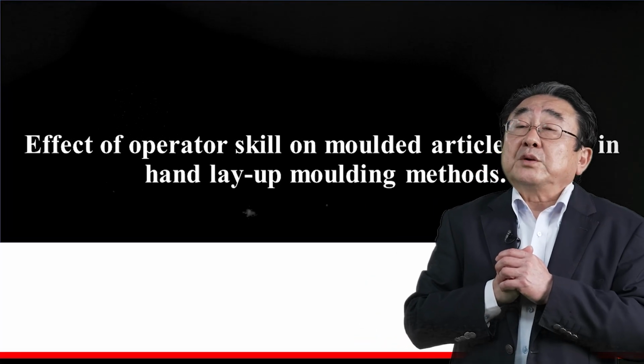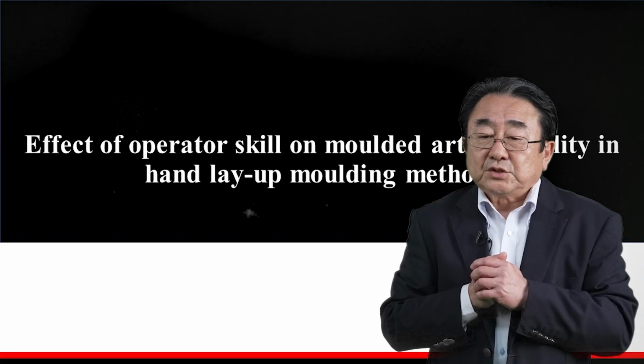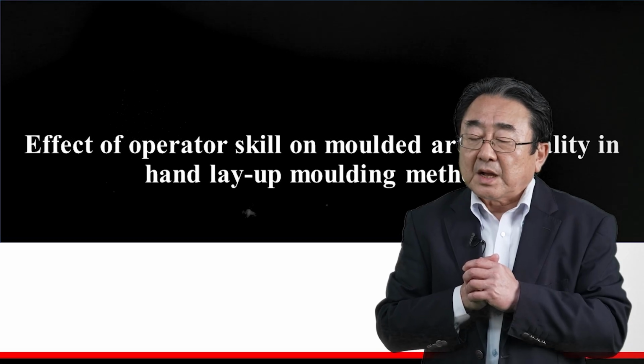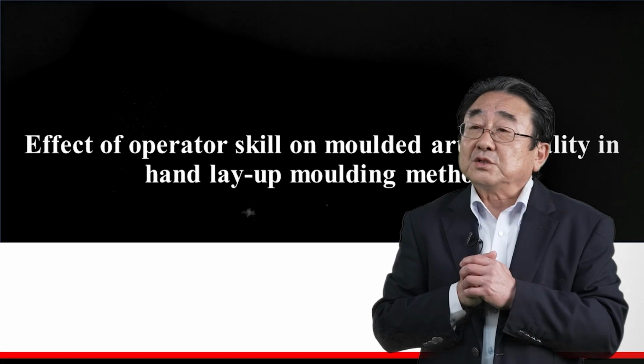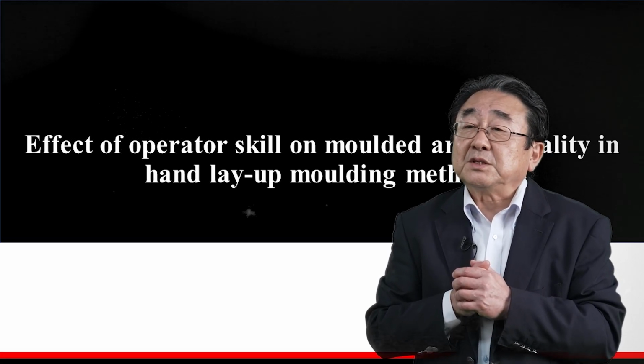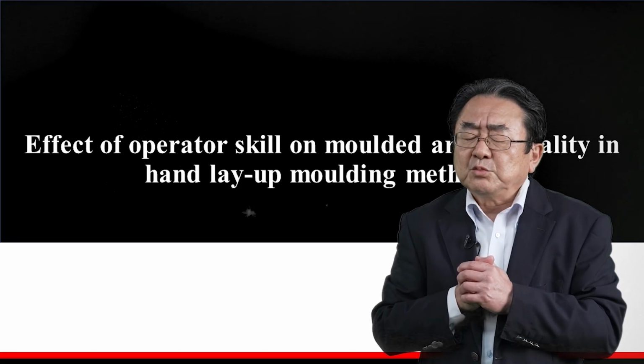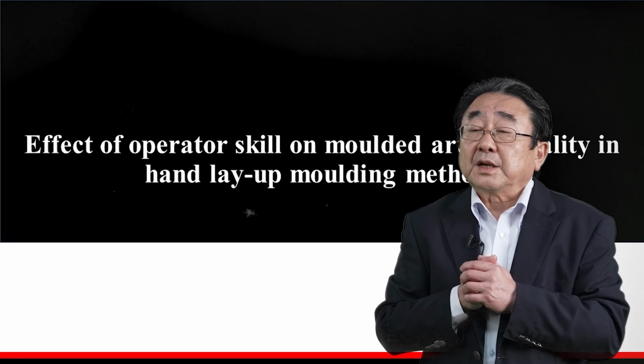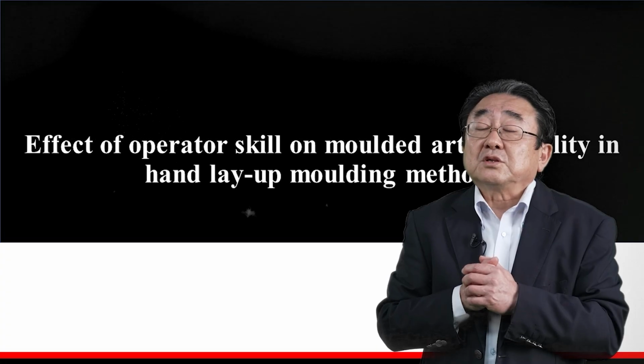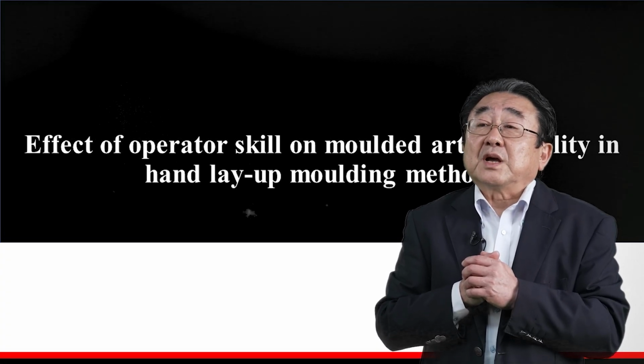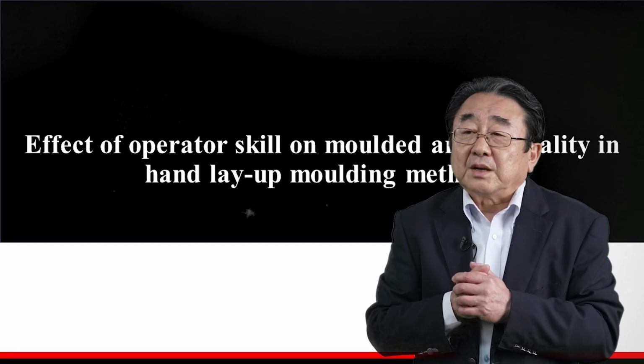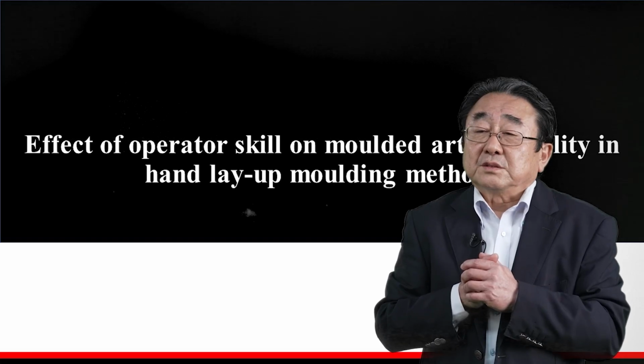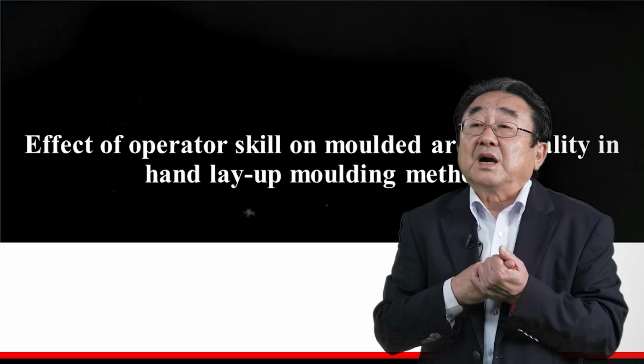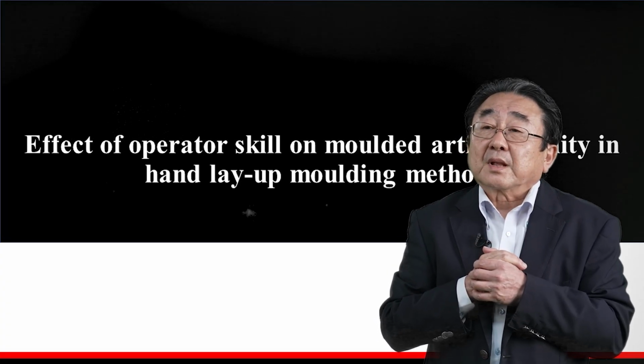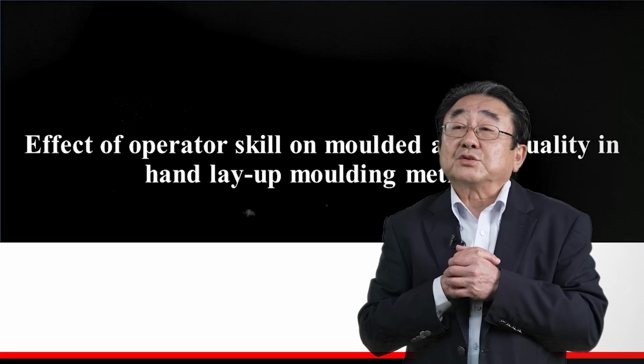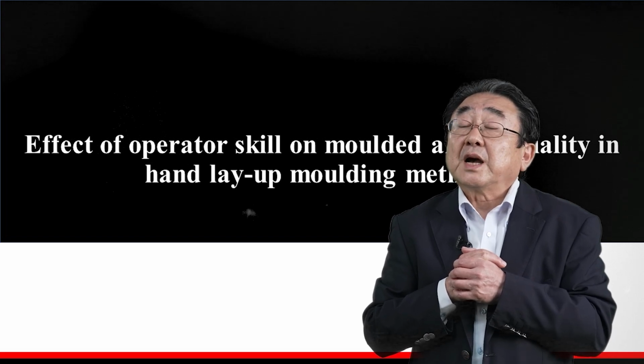So the rolling of the steel roller in the hand lay-up method, I explained that is an impregnation stage. But that impregnation stage means not only removing the air from the inside of the FRP, but also making a good interface. So the hand lay-up method, using a steel roller, has two roles. One is impregnation. One is making a good interface. And then finally, the expert, the person who can make a good interface, that person's specimen shows the higher mechanical properties.